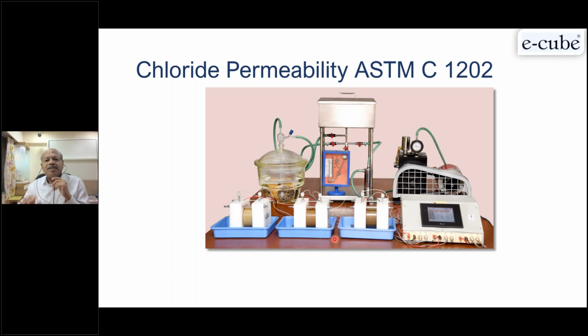That is a very simple test, but the condition is important. You have to see your conditioning of the specimen is very important in this, because you have to put an appropriate capacity of vacuum pump. If that vacuum pump is not proper, if the condition is not proper, you will not get proper results. So we have to see, whenever you are going to witness the test or anybody is doing the test, you have to see first, this is only a voltage, and the important thing is your vacuum. If you are able to manage the vacuum properly, then only you will get proper results.